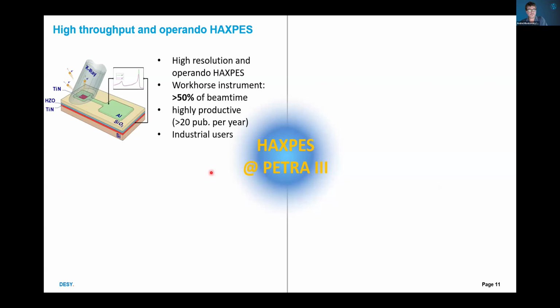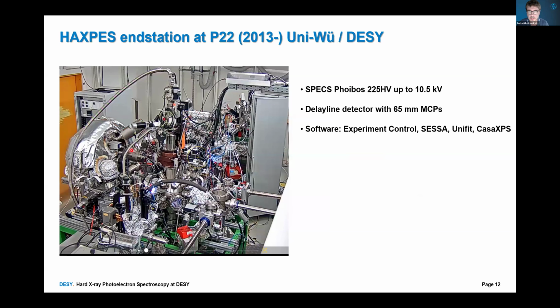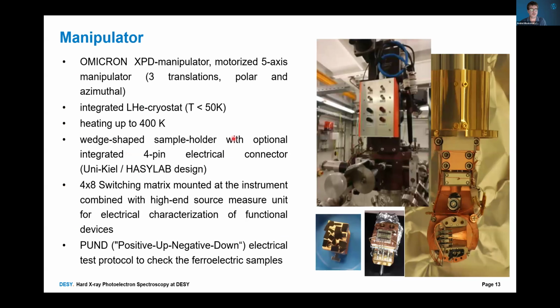So as I told, we have 4 instruments at our beamline, and the first instrument is the large hemispherical analyzer, which can analyze photoelectrons up to 10.5 kiloelectron volts. It has a large delay line detector with 65 millimeters microchannel plates to detect all possible electrons after the exit slit. And we offer multi-platform experiment control, which controls both our beamline and analyzer. And also we have a lot of software for simulating the photoemission spectra and for analysis of the spectra, for fitting them to Gaussian and Lorentzian shapes.